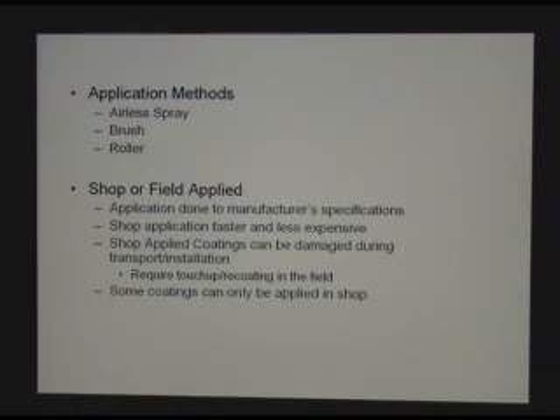The paint is applied typically by airless spray, by brush or roller. Airless spray is what we prefer because it's the fastest method. But in the field, quite often we cannot do this because of concerns overspraying other items. So quite often we have to brush paint entire plants with a much slower method. We try to apply our paints in the shop as much as possible because it's less expensive overall, even though you have to allow for additional expenses for touching up the shop coatings in the field. But of course, there are some coatings which can only be applied in the shop.